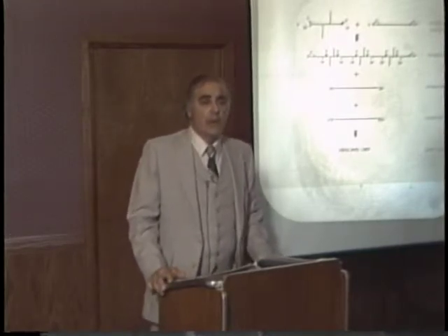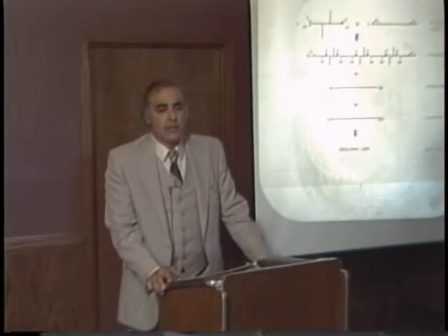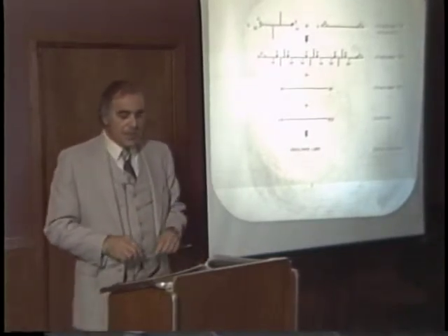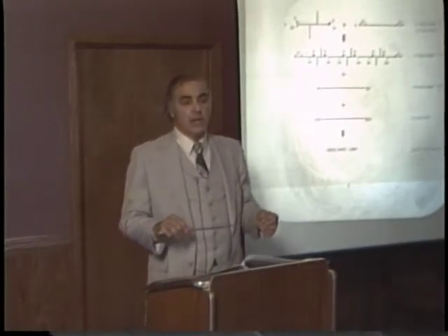Now, in this particular program, although we were concerned with barrier properties of liners, the applicability was to the tactical environment, specifically in concentric grain design, where we would actually put a liner between two grains. And the requirement for a material like that is that the liner have a modulus at minus 65 degrees Fahrenheit comparable to that of the propellants that it lies between, or sandwiched between.